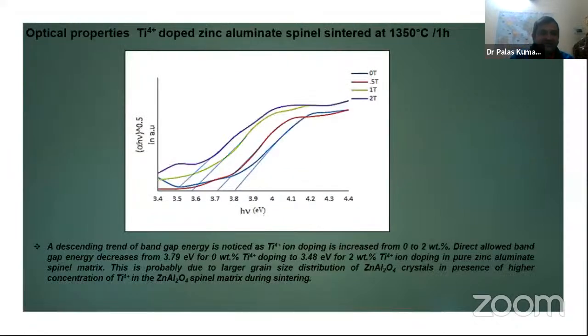And lastly, coming to the optical property, yes, we also measured the optical property of titanium doped. Of course, we measured zirconia, but I displayed the titanium. This is the more important, more interesting and promising, titanium doped zinc aluminate spinel. This is the very familiar Tauc plot. The y-axis is alpha h nu, alpha is the molar absorption coefficient, and the x-axis is the energy absorbed, h nu. Where this line, if we extend the line, intersects the x-axis, this will be the band gap energy.